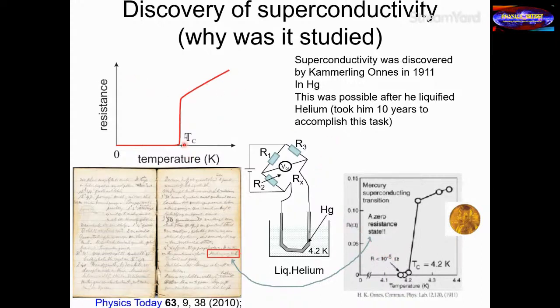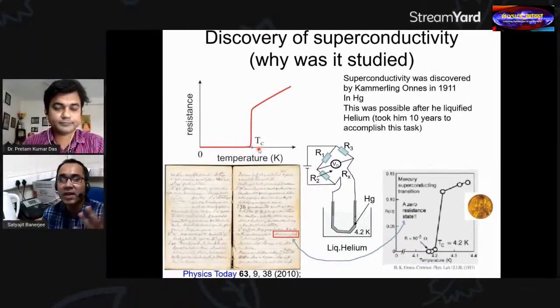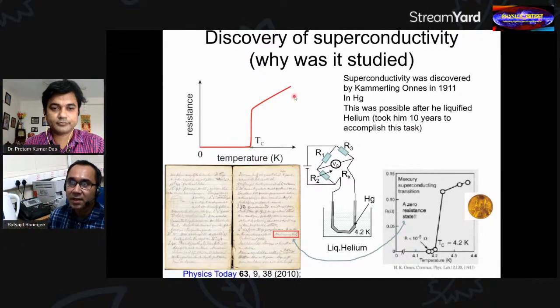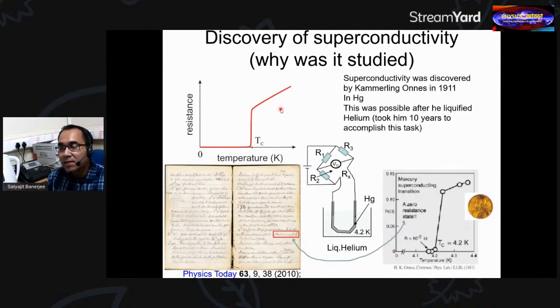So this is the transition of a material into a zero resistance state, or what looks like a zero resistance state. It becomes immeasurably low. So this was the birth of superconductivity, a fantastic phenomenon in which suddenly the material loses all resistance. And you know that resistance comes because electrons are flowing inside the metal and they are hitting atoms or undergoing collisions, and that gives rise to resistance. So below the superconducting transition, suddenly the metal loses all its resistance. Okay, there is no resistance which is experienced by these electrons, and they can just flow without any resistance.